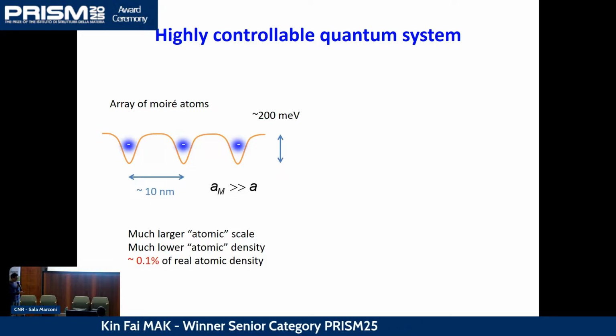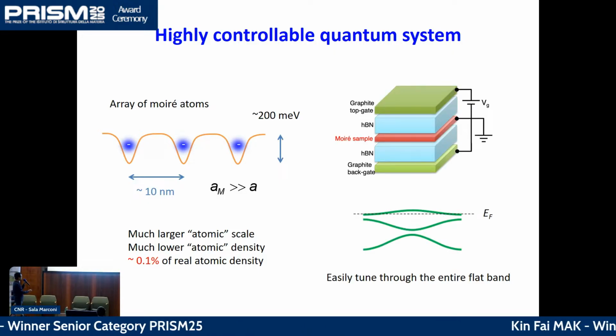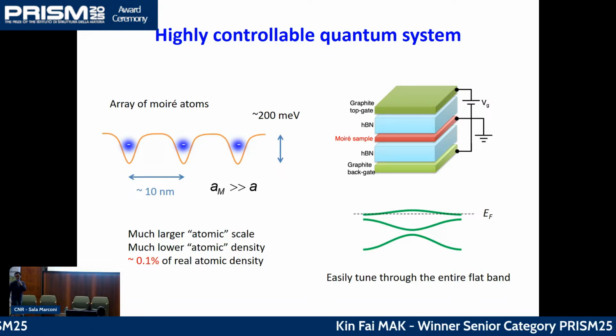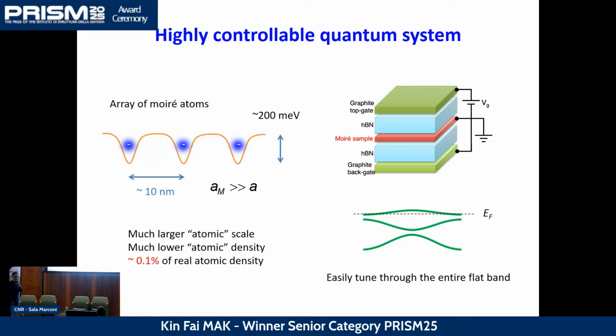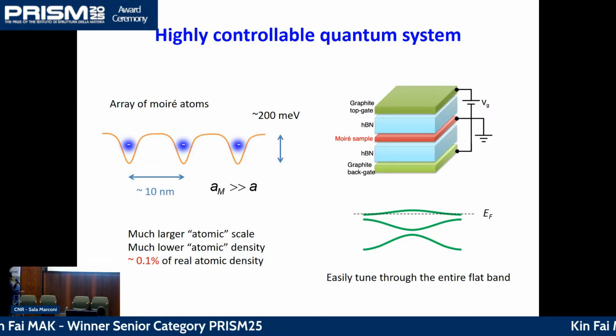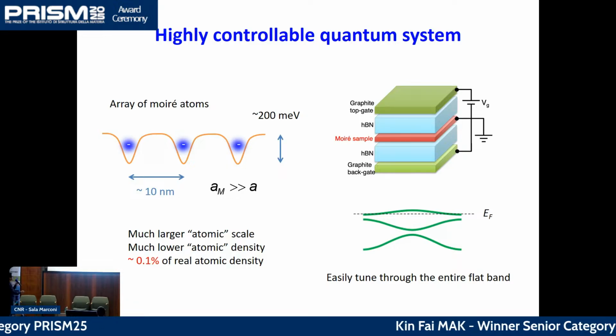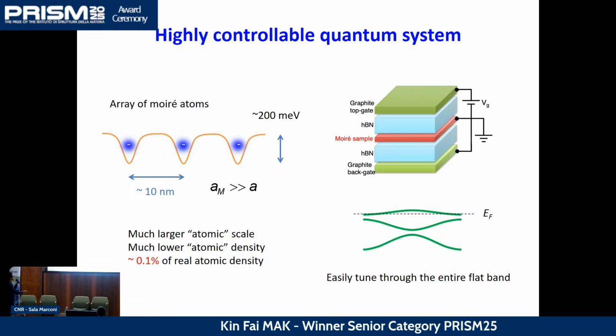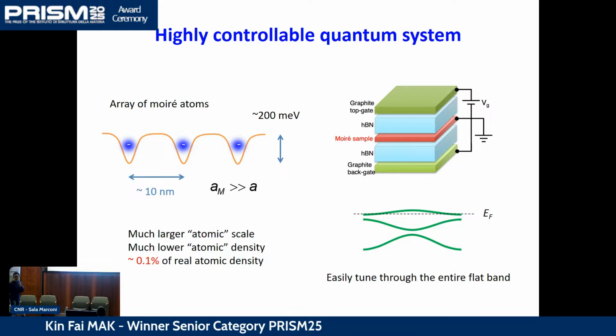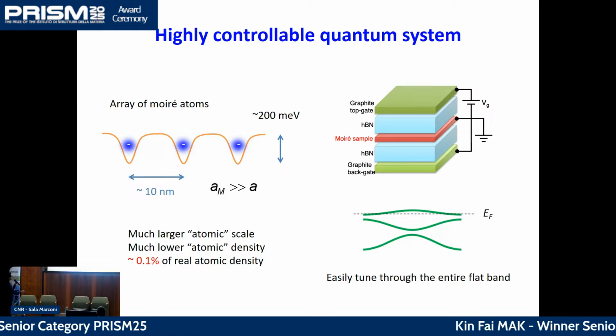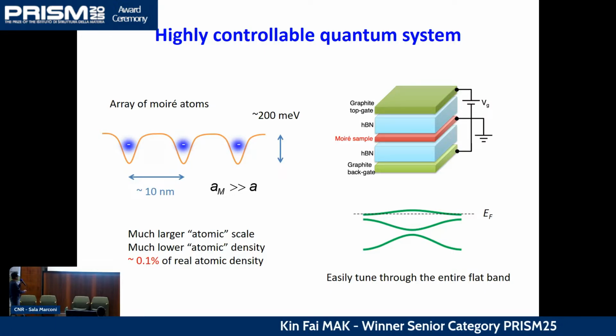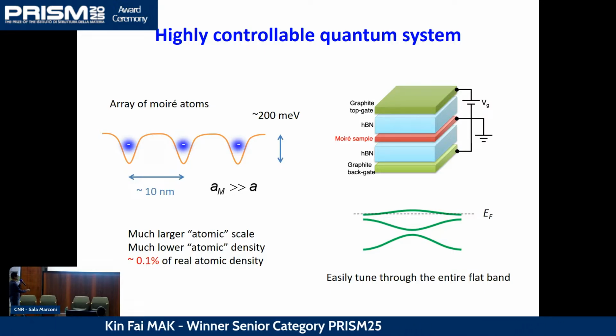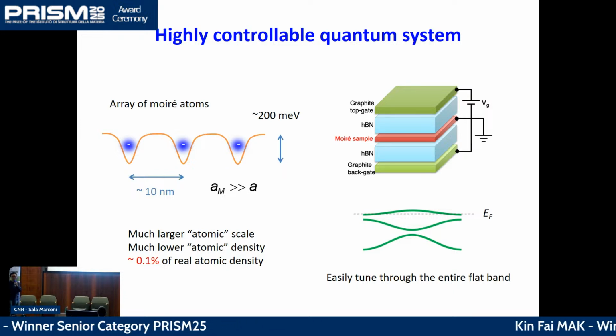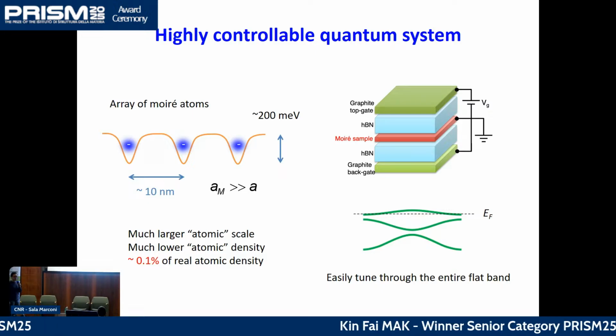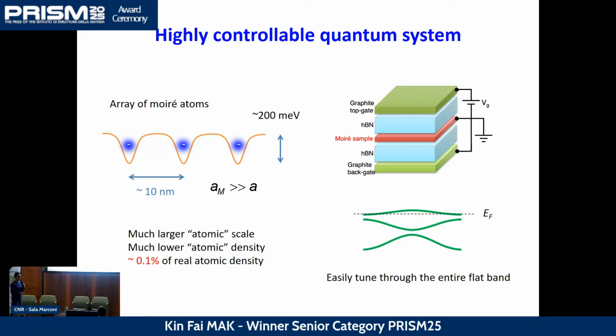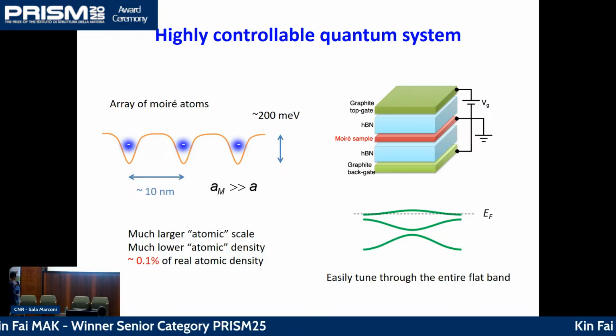Okay. In a typical device structure, we have our moire sample sandwiched between boron nitride. Boron nitride is a very good insulator. It has about a 7 electron volt band gap, so it acts as a gate dielectric. On top of that, we also put extra metal electrodes to create this kind of capacitors-in-series structure, to be able to tune the density continuously in the material by just applying voltages to the gates. And because of the much smaller atomic density in this kind of artificial material, with this kind of gate you can move the Fermi level through multiple flat bands, which is something that you cannot really do in real materials. You cannot really use a gate voltage to tune the Fermi level in a real material, not even through one band. But here you can go through multiple flat bands.